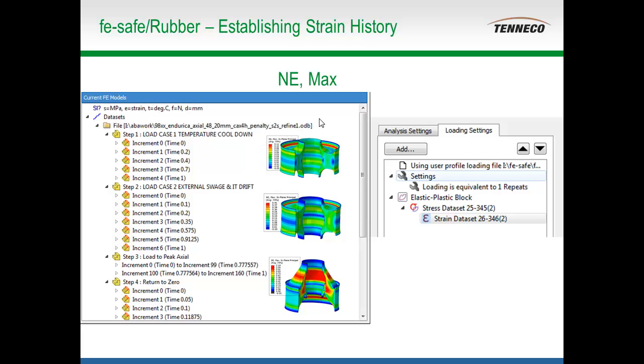The material testing that's required, basically everything I showed here, but then at elevated temperature or multiple elevated temperatures, and then all of that testing, or a good portion of it, at multiple aging conditions. So once you start to want to model the effects of temperature and aging, the amount of material testing starts to grow exponentially. So we are just setting up, and actually we'll be testing our first complete environmental set of material properties in the next couple weeks.